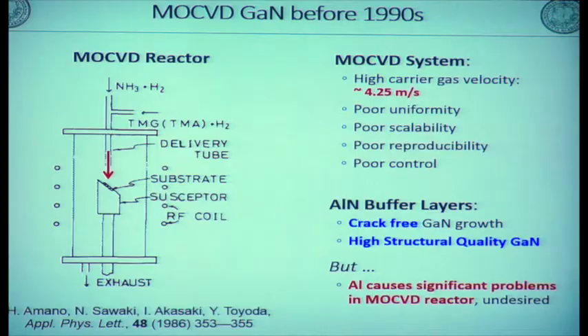So my dream was to submit at least five scientific papers. But if I select zinc selenide, there is a huge number of papers, so it was impossible because I had never published papers. But if I select gallium nitride, there were almost zero papers. So it's easy to publish a paper; any kind of result I could publish. But I never expected I could invent blue LEDs. So that's the reason I selected gallium nitride. And so I started the gallium nitride blue LED research in '89.